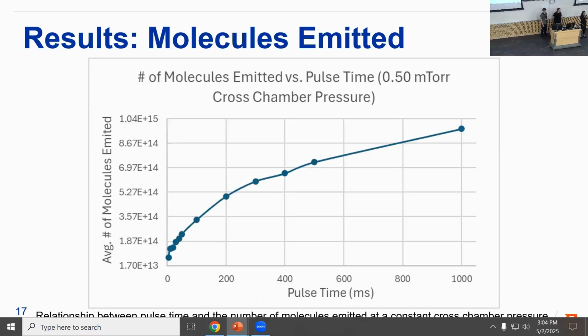Okay, so here we have the relationship of pulse time versus number of molecules emitted. Initially, the number of molecules emitted rapidly increases, and then as you can see, as the pulse time continues to increase, the rate of increase in the number of molecules starts to slow down. This variation in the emission rate could be due to the efficiency of the pneumatic valves opening and closing times, depending on the pulse time, or the fact that the gas behavior may be changing altogether.